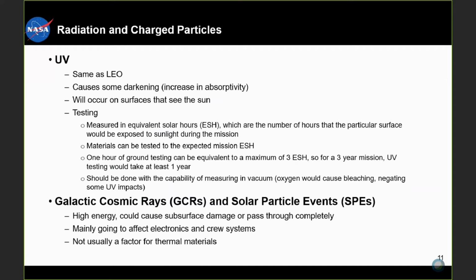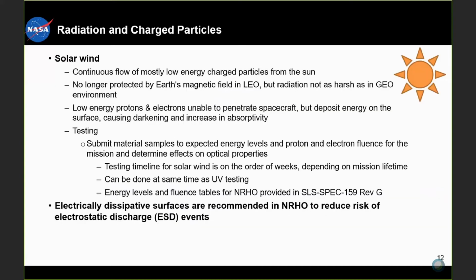But because they're high energy, they could mostly cause subsurface damage or pass through completely. So surface damage is what really matters for optical properties, so it doesn't really affect it that much. It could, but it's not as big a deal as the surface degradation from other sources. So it's mainly going to affect electronics and crew systems. You should definitely be worried about it, but for thermal surfaces, not so much. So it's not usually a factor for thermal material coatings.